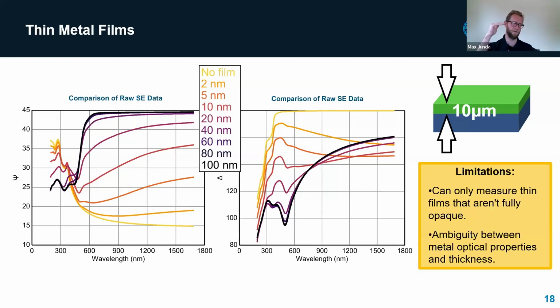That's as the metal film is getting thicker and thicker. And you can see going from the case of 0 thickness up into about 50, 60 nanometer range, the spectrum is changing quite a bit. So we're getting sensitivity to the thickness and how it affects this measured data.